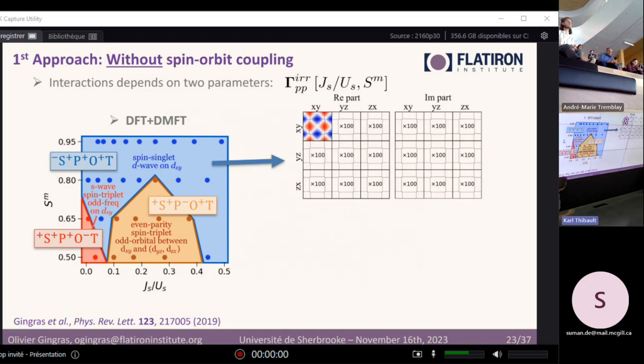and it's essentially a d-wave on the xy orbital. So the way to read this gap function that I show: first, there's a real and imaginary part. And Cooper pairs here have two electrons, which can have three different orbitals, xy, yz, and zx. So here, this 3x3 matrix shows which orbitals are used to construct the Cooper pairs. And in each of these squares, it's the momentum structure of this component of the order parameter. So here you see that this blue region is really a d-wave, where you have dx² minus y², purely on the xy orbitals.